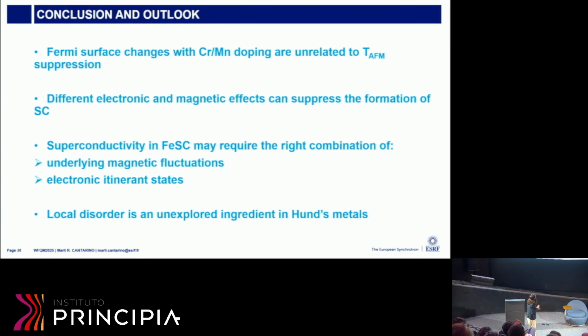From this, I try to speculate a little bit, because in this work I don't consider bond lengths, angles, or chemical pressure, nothing of this sort. And we know this is important—the iron arsenide distance, for example, is very important. So I don't go into this side of the study, but I conclude that for these materials, they require the right combination of underlying magnetic fluctuations and electronic itinerant states to allow not only the necessary conditions, but some of the sufficient conditions too.